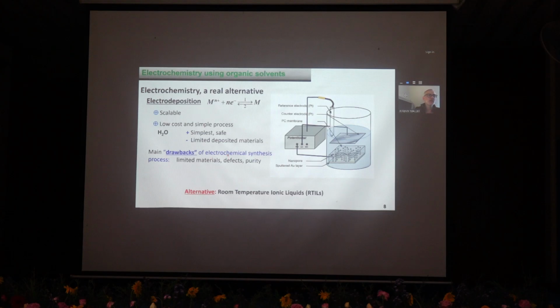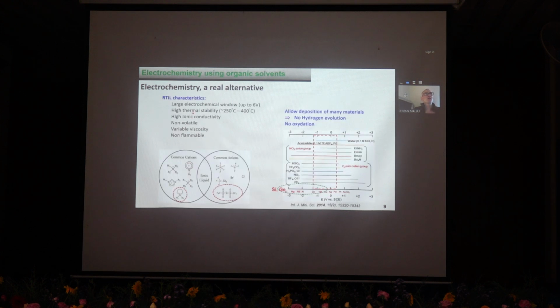This limitation can be solved by using alternative solvents such as organic solvents, for instance, room temperature ionic liquids. So that's what we've been working on for the past 10 years. We use mainly ionic liquids that have a very large electrochemical window, up to 6 volts, high thermal stability, very good ionic conductivity, which makes them suitable for electrodeposition or electrodissolution. Non-volatile, not very high viscosity.